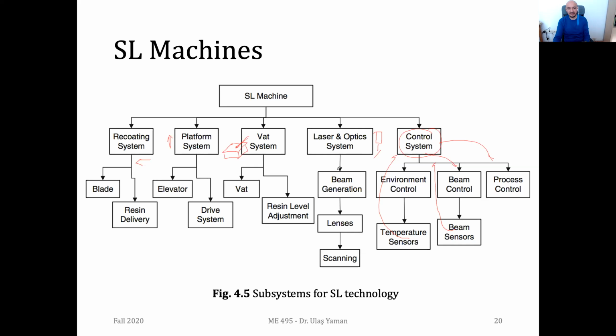And in the laser and optic system, we have beam generation, obviously, in this box. The laser is generated, and then this laser is reflected through the lens on the XY plane. And for the vat system, some printers have resin level adjustment systems. They check the amount of material in the vat. If it's low, then they open a gate at the bottom of the tank so that more material will be poured into the tank, and they will continue with the curing operation.